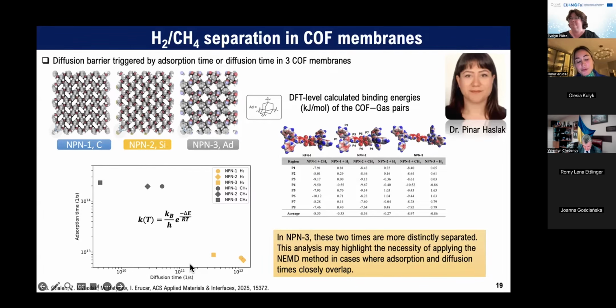On the y-axis, we can also see diffusion time. Here we took the self-diffusion coefficients that we computed from equilibrium molecular dynamics simulations, and we divided the pore limiting diameter squared by them, so we get the diffusion time. And we recognize that, for example, in NPN3, these two times, adsorption time and diffusion time, are more distinctly separated. So we can argue that the application of the NEMD method can be important where adsorption and diffusion times closely overlap. This can be critical when you do this modeling. And Dr. Pinar Haslak also performed all these DFT simulations.